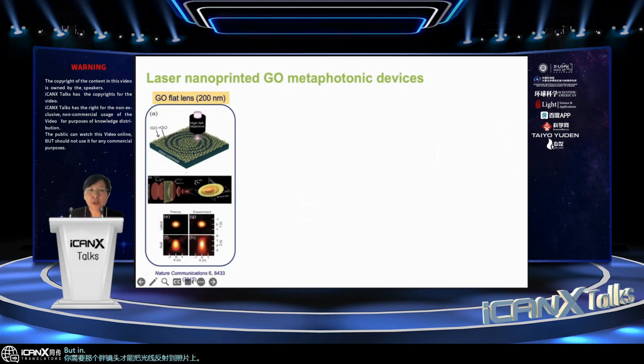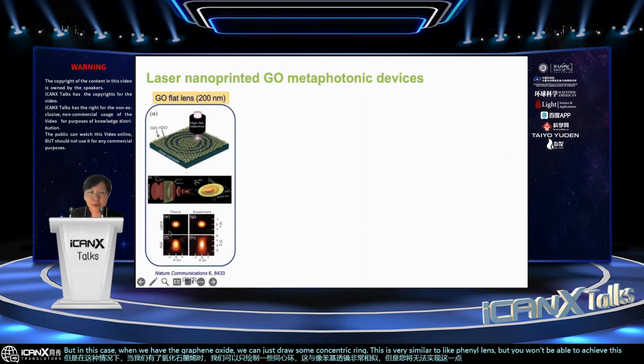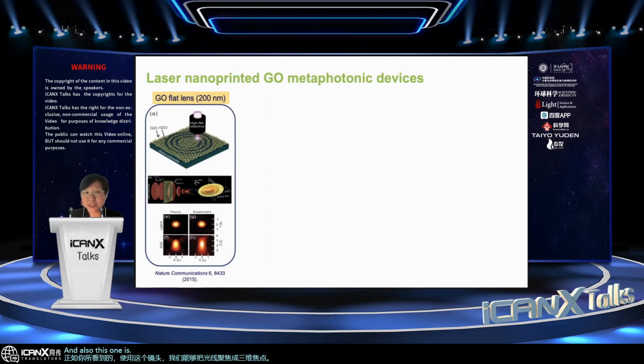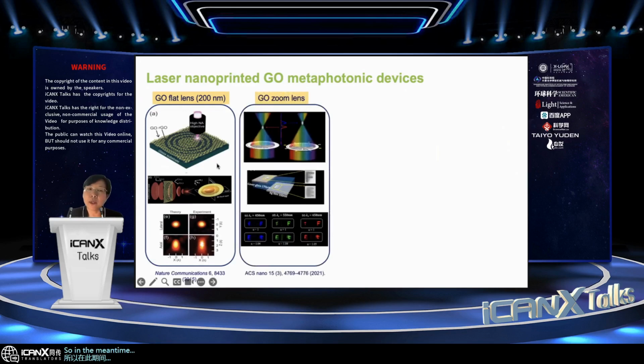But in this case, with graphene oxide, we can just draw some concentric rings. This is very similar to a Fresnel lens, but you won't be able to achieve this very nice focusing with a Fresnel lens. As you can see here, using this lens, we're able to focus the light into a 3-dimensional focus. And this one is diffraction limited. That means the resolution is really high. This is because of the benefit of having the large refractive index change and also the extinction coefficient increase.